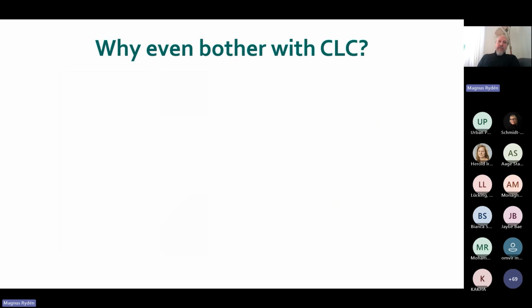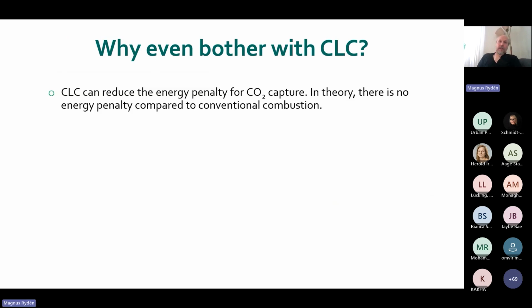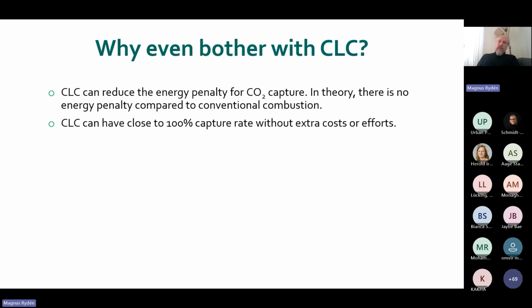So why would we bother doing this? The reason why we want to do this is to reduce the cost of CO2 capture. And this we could do very significantly with CLC compared to post-combustion. In theory, since we don't mix air and fuel, there is actually no energy penalty compared to conventional combustion for CO2 capture. We can also achieve a high capture rate. For absorption-based technologies, you have some kind of diminishing returns when you reach very high capture rates. This does not occur for CLC, so here we can reach close to 100% capture rate.